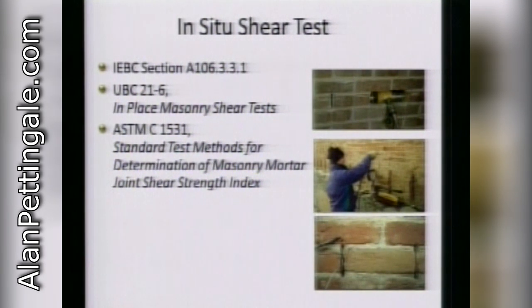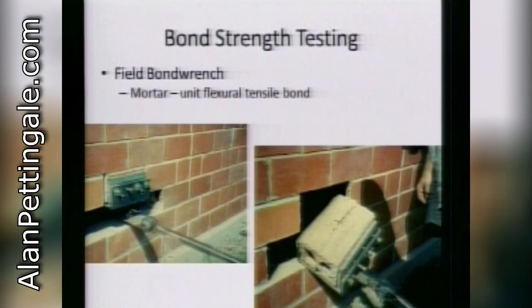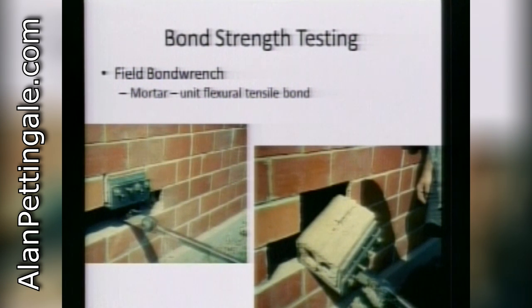There is actually a shear bond test mentioned in the International Existing Building Code — in some cases, if you read between the lines, it's actually required. This is a more mechanical, hands-on test: you expose a brick unit, apply a wrench, and physically measure the force it takes to wrench it out from the wall, measuring its flexural strength. The flexural strength of unreinforced masonry can be exceedingly good if you have a skilled mason who understands good bond and has generations of experience.